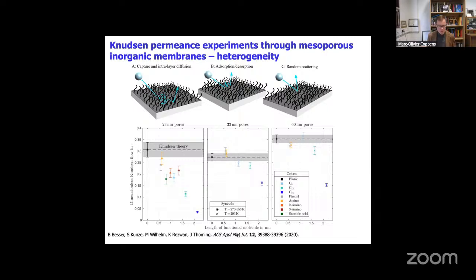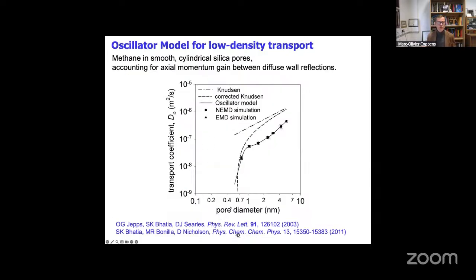Another aspect that goes even deeper in fundamental theory that I want to highlight is the work of Suresh Bhatia and Nicholson, who have done a lot of fantastic work in this area, looking at mesopores. They have this so-called oscillator model. It would take me too far to describe this to you, but I refer to their papers here for you to check in more detail, because what they mention here is that even if you have a smooth cylindrical pore, you can have axial momentum gain between different diffuse wall reflections, and you may need to account for that. So in certain situations, you really need to account for that, and otherwise you get disagreement between purely geometrical models and these more physical chemical models. And they validated this both with equilibrium and non-equilibrium molecular dynamics.